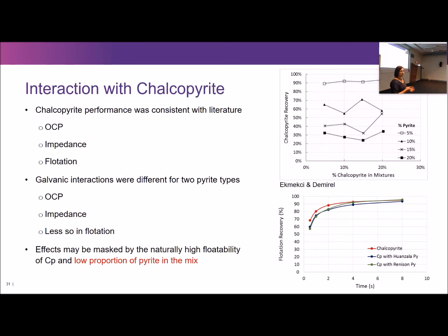So, what's happening with chalcopyrite? Well, chalcopyrite performance was entirely consistent with literature. If you put in more pyrite, the floatability goes down. We have confirmed what was found by at least 3 other researchers, so yay, we have consistency. We saw this also, not just in floatability, but in rest potential measurements and impedance measurements, all confirmed what we saw in the flotation cell, which is always nice. And it galvanically interacted with different pyrite types to a very different degree. Again, we saw this in rest potential, impedance, and flotation to a lesser degree.